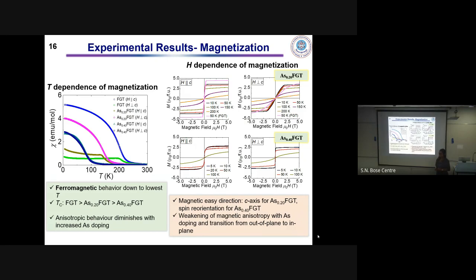Because in FGT, the topological Hall is observed only when the magnetic field is perpendicular to the c-axis, along the hard direction. In this case, totally I agree. It is almost impossible to get the value of the topological Hall, because your resistance is not following anything about this behavior.